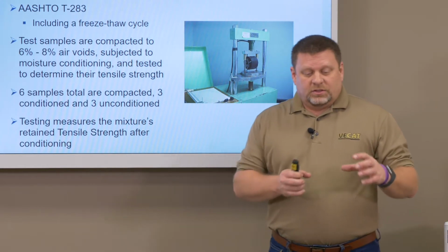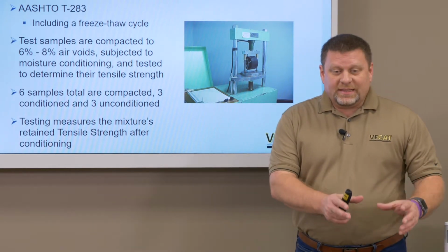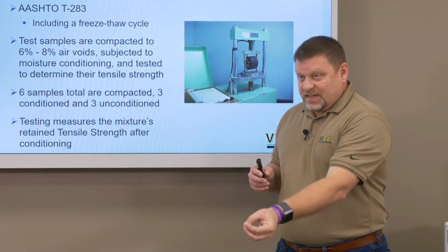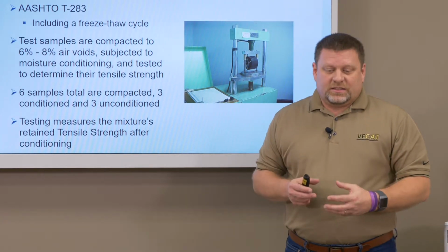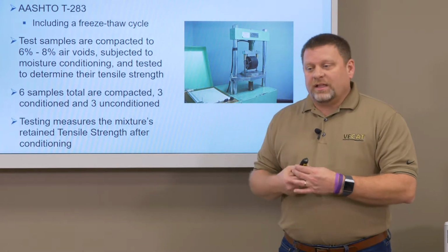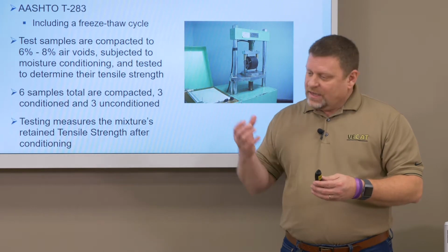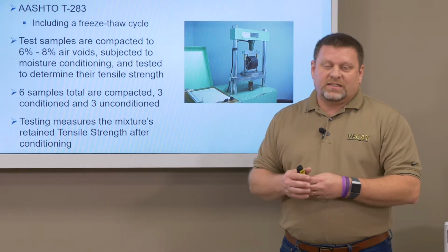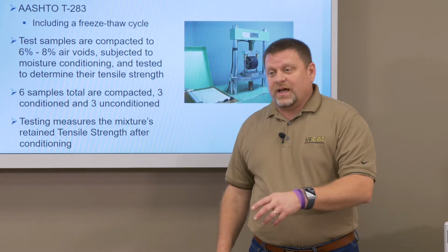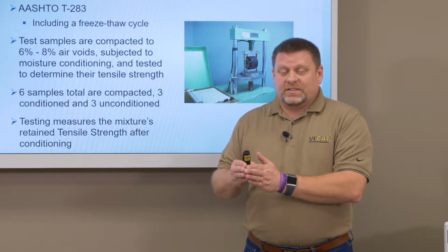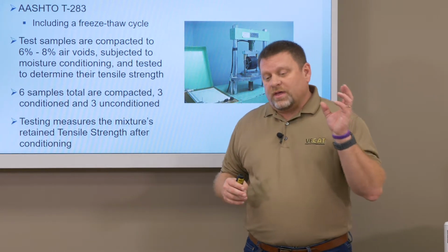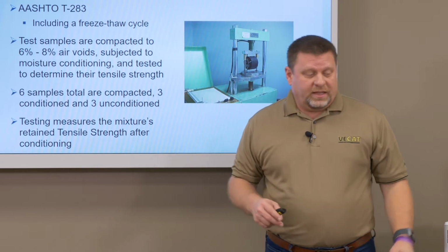So when I take these samples out of the hot bath and I put them in the 77 bath, these specimens can heat this water up. Most likely you'll need to add a few cubes of ice. I typically would have a 16-ounce glass, a cup of ice, nothing but ice in it, and I just dump the ice in that water at that time because I want to maintain that 77 degrees. I don't want the temperature to elevate too much. So when I do that, I put them in the water bath, I'll add a little bit of ice.